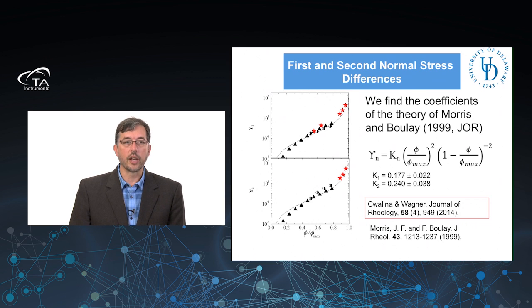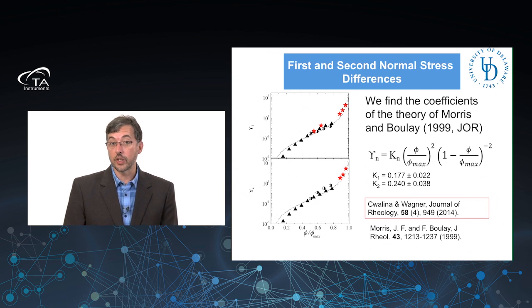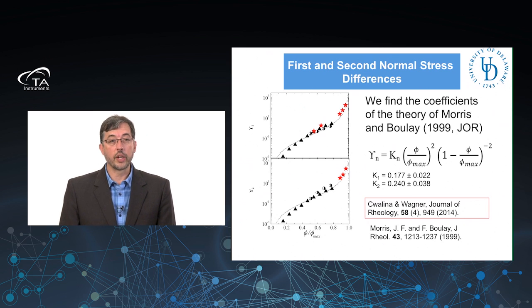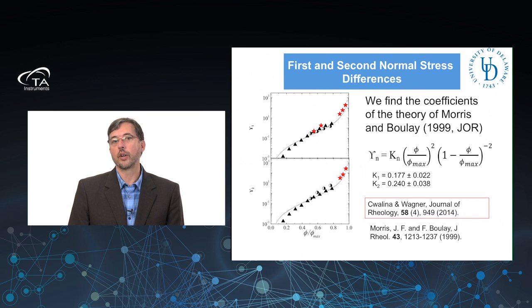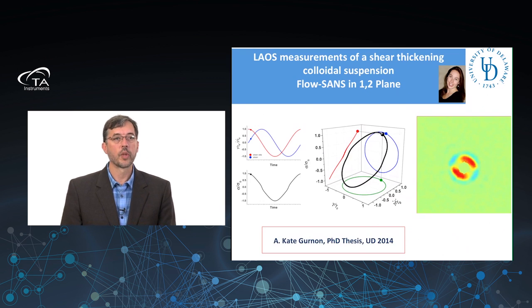And you can see that, again, the shear thickened state lines up very nicely with that of non-Brownian suspensions, and follows the scaling law, which are the dashed lines shown there, and there are the coefficients we've determined and published there. So we now have a very good idea about the rheological properties of that shear thickened state. It looks like that of a non-Brownian suspension, maybe not so surprising. But the effective volume fraction of that state is much higher due to the trapped liquid in the hydroclusters.